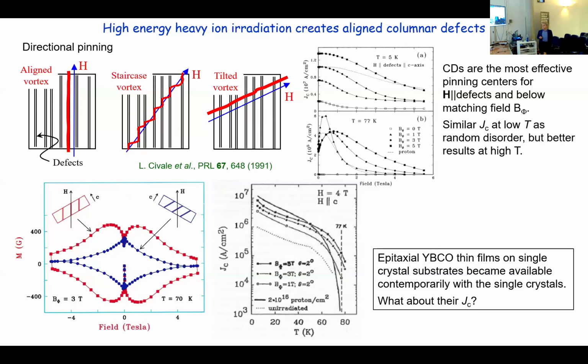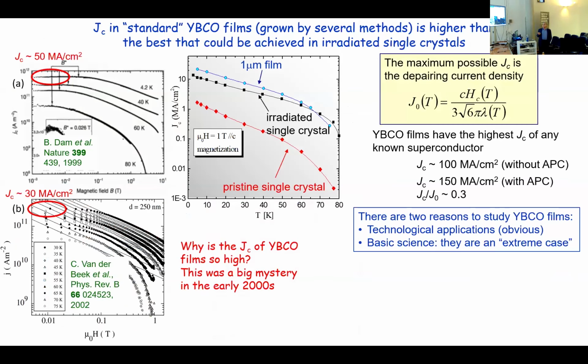Now, at the same time that the single crystals appeared, the YBCO thin films started to appear. And then the question is, what happened with their JCs? Well, it soon became clear that the critical current of standard YBCO films, grown by several different methods, was not only high, it was higher than the best that could be achieved in single crystals with any kind of irradiation. And that started to become obvious around the year 2000.